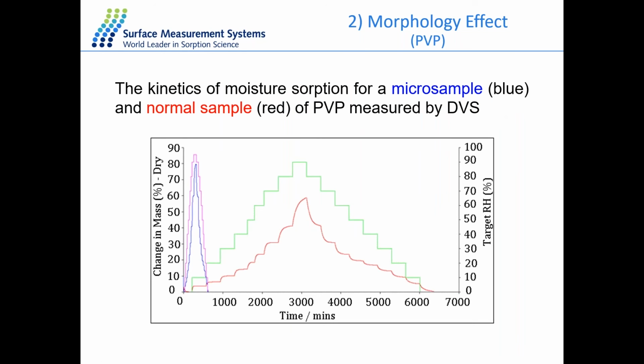And here's the result for the two PVP samples that we ran at 25 degrees from 0 to 95% RH. The blue line is for the micro PVP sample and the red line is for the normal PVP sample. This data clearly demonstrates that sample size very dramatically affects the overall speed of analysis. In this case, we decreased the sample mass about 50 times for the micro PVP sample. Then the analysis time for the micro PVP sample is almost 10 times faster than the normal PVP sample.